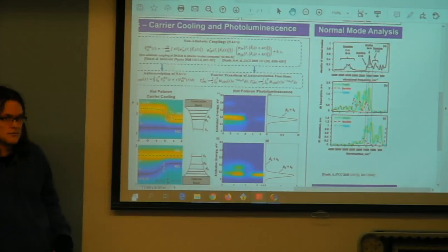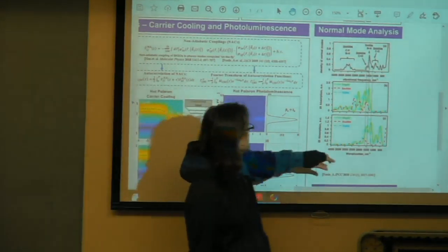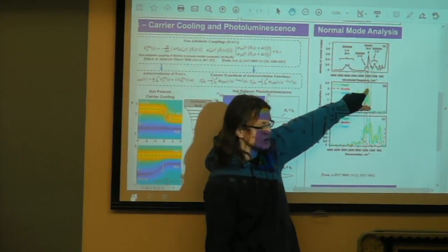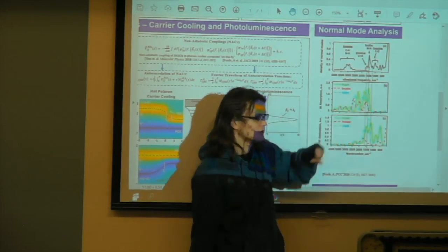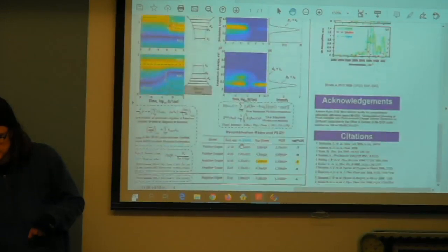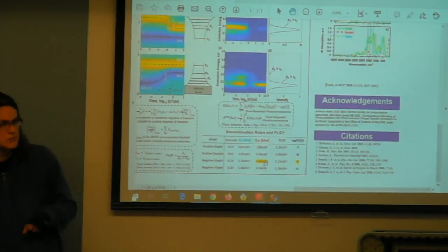So yeah, my interpretation would be that anywhere you have carboxylate contributions in the normal mode, those would be significant, whereas the ammoniums, even though there's a big peak there, don't contribute that much. So the singlet doesn't have any active vibrational modes in resonance with it, while the triplet does. That's how I explain the two orders of magnitude difference in the non-radiative recombination.